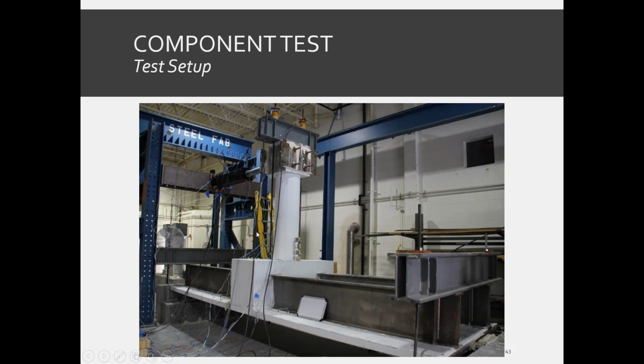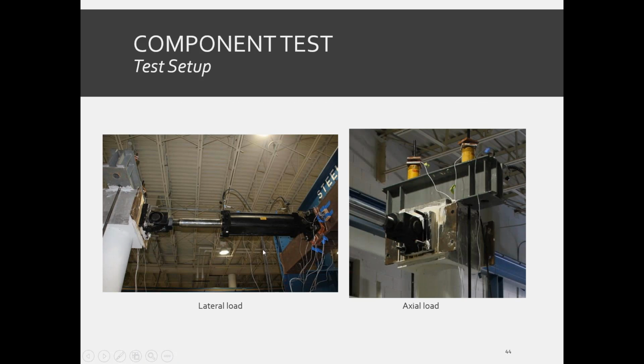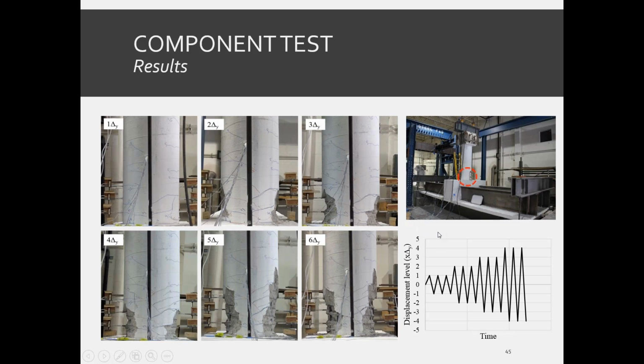The next step was preparation of the test setup. The lateral and axial load mechanisms were put in place. You can see here the actuators used for lateral cyclic loads, and we had the hydraulic rams to apply axial loads. The crack formation and propagation was mapped during the entire run of the experiment at the maximum displacement level in each cycle. This is the area which you're looking at in these pictures. This is the region where the plastic hinge occurs in the column.